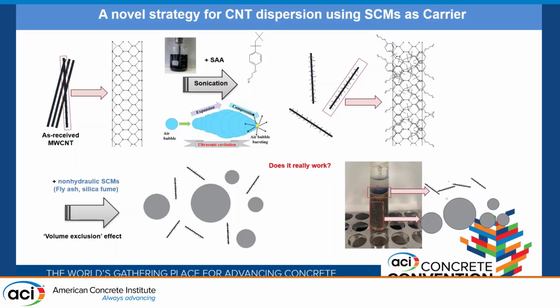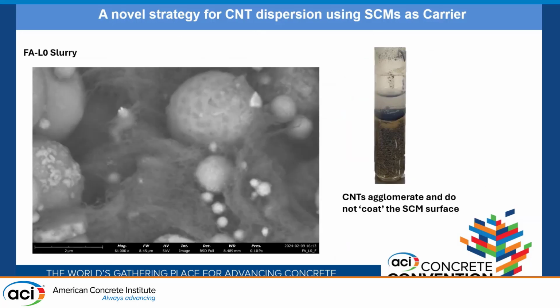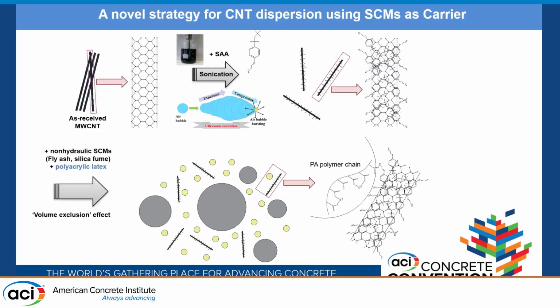After about a day, it's still separated. Now we see the deposition of the SCM particles on the very bottom, and then the carbon forms a layer, and everything is separated. Second, we took some slurry, put it under SEM, and can clearly see fly ash stays fly ash. There's nothing really attached to it, and all the nanotube is still agglomerated around it.